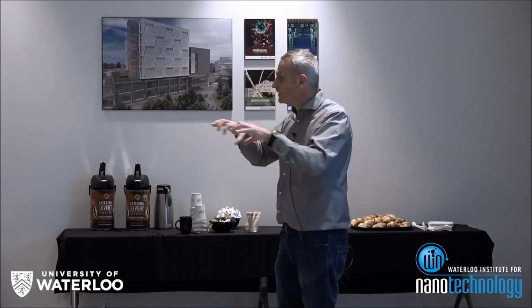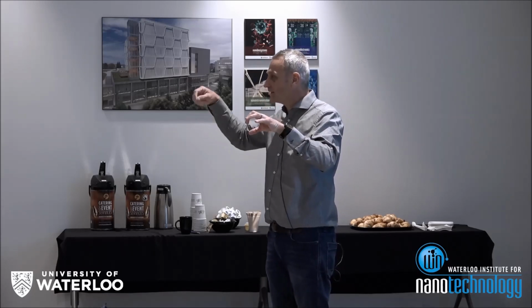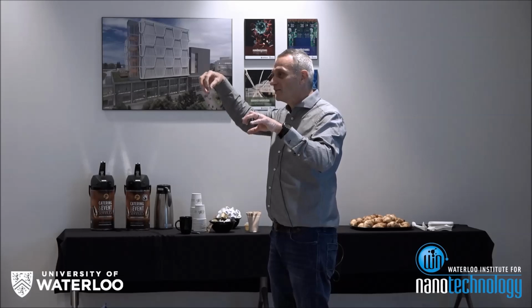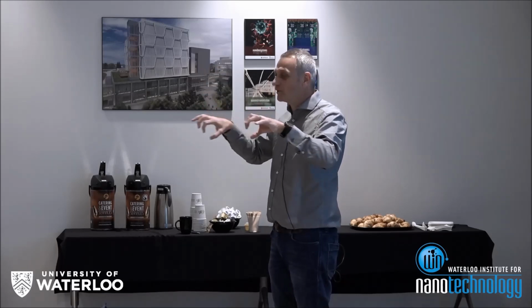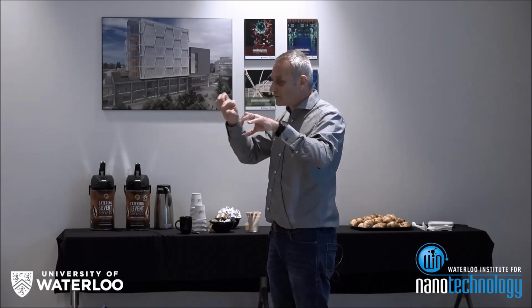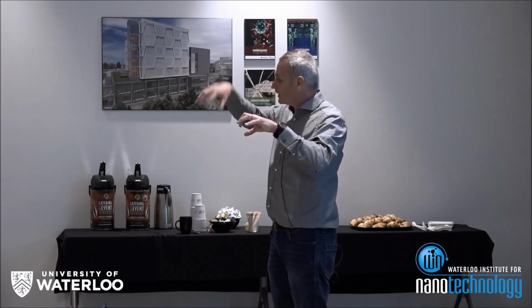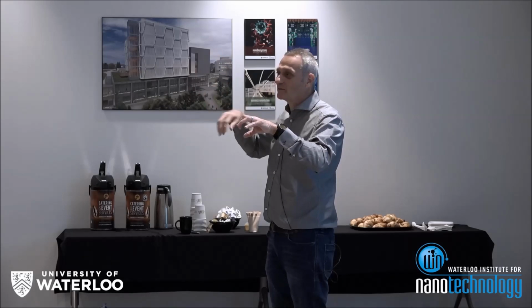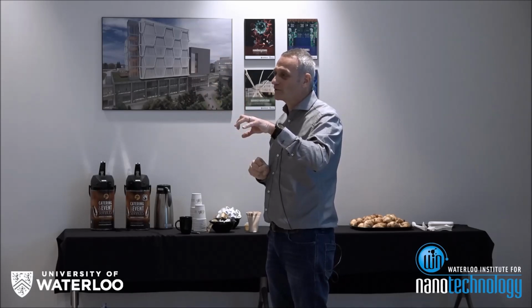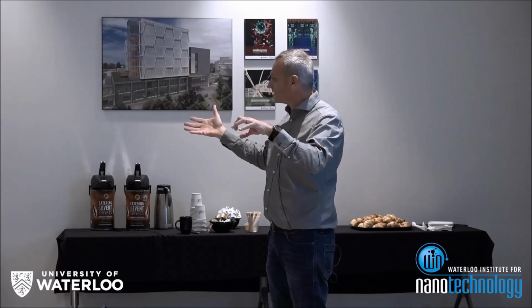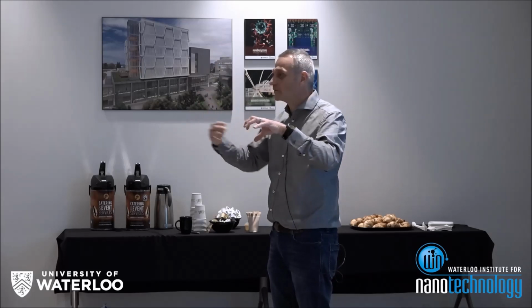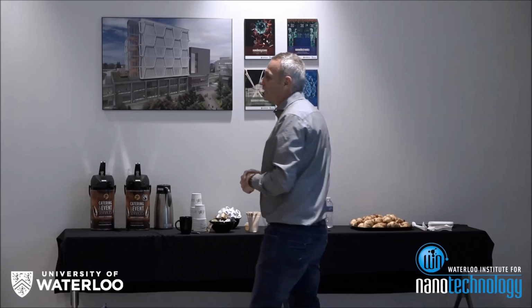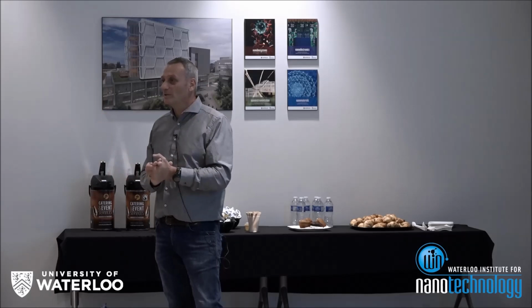Sometimes, even at 600 degrees, silver nanowire is still stable, but sometimes there's a leak, and silver goes outside. So with a TEM, for example, we can see a shallow cylinder with just the PVP, and then a bigger particle of silver here, because again, the silver just wants to minimize the energy of the system. If you have big particles like this, it's much better in terms of surface energy compared to filling the whole hollow tube. And for us, that's a big problem, because we don't want to see big metallic particles. They will make short circuits, be very opaque, and not help the conductivity.